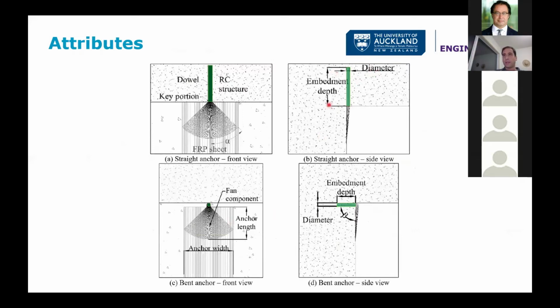And the diameter and the embedment depth are going to determine the capacity of the anchor related to the dowel. Then we have the fan portion, where all the fibers are fanned out and bonded to the sheet behind. And we can make wide anchors or we can make narrow anchors. And that width is determined by fanning angle alpha, which I specify as half of the fan, and you will see why in a few minutes. And then the part of the anchor where the fibers transition from the dowel into the fan is usually called the key portion, because it's where all the fibers will break if we have fiber rupture failure mode.